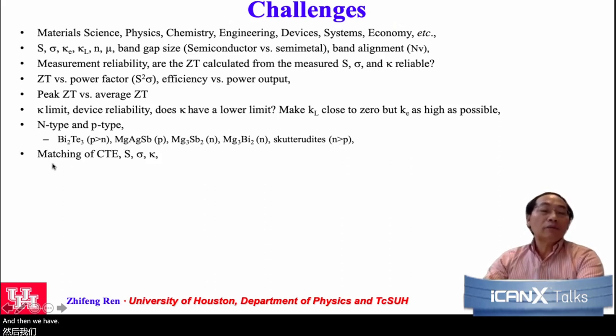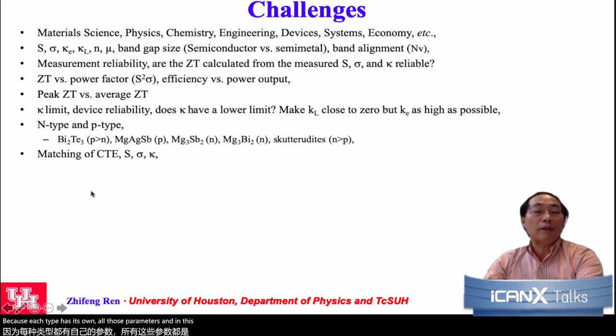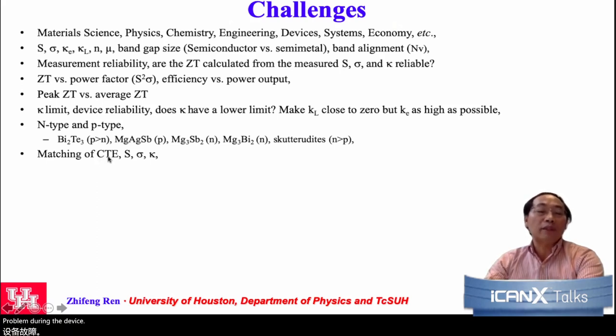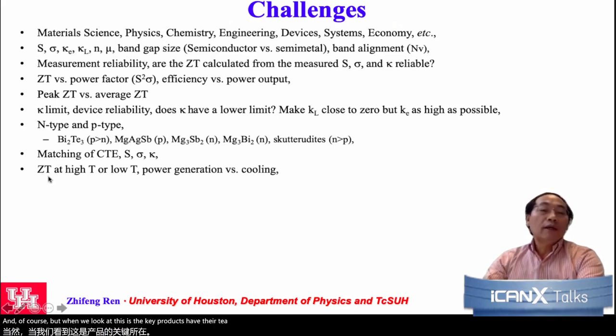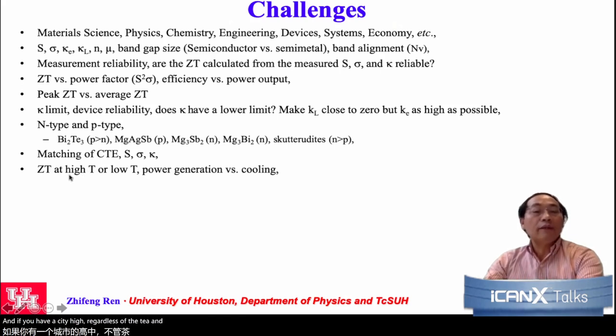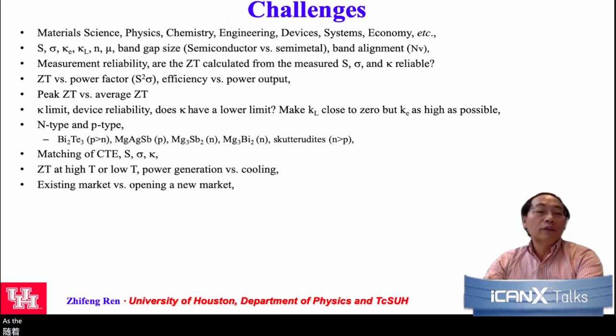And then we have to worry about the matching of the two, both N and P materials, because each type has its own parameters, and these parameters have to be well matched. If they are not matched, then you are going to have a problem during the device assembly, which is why we have to look into that. And of course, ZT is a product of Z and T. Higher T is for power generation, lower T is for cooling. If you have high ZT regardless of the T, then you can do either power generation or cooling, which is very important.